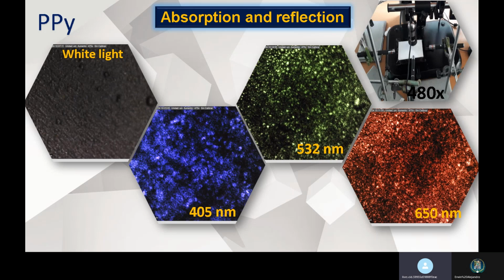The materials were illuminated with white light, blue light at 405 nanometers, green light at 532 nanometers, and red light at 650 nanometers. Dark zone has a relation with absorption, while bright zone with reflection. Polypyrrole was illuminated with white light, and it's possible to see a dark zone with small particles in this image. Polypyrrole was sensible in all lights.